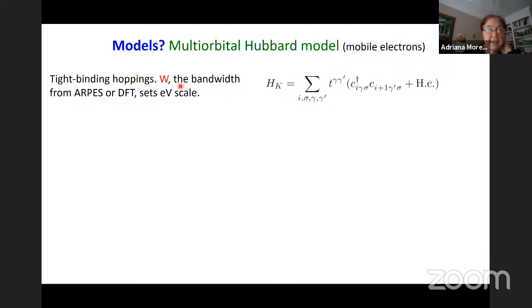So the energy scale W is obtained from angular resolved photoemission experiments or from DFT calculations, while the hoppings and the terms that appear are obtained from the geometry of the lattice and the orbitals using, like, a Slater-Koster calculation, for example.